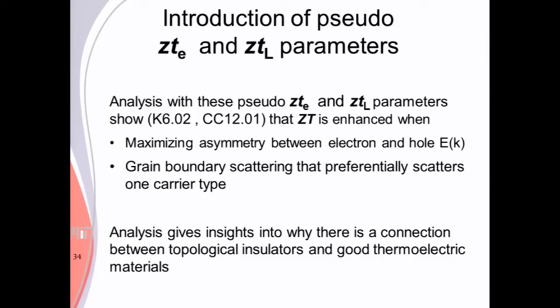We have scattering systems like grain boundary scattering. That's one that is very important because we make smaller and smaller grains to get higher ZT. Is there a way that we can generate or engineer these boundaries so that they preferentially will scatter carriers of one type? So we can make it p-type, n-type, and will also scatter the phonons much better than the electrons. So now breaking the system into these 2 components makes it easier to do the calculations than before. That's what we are finding.